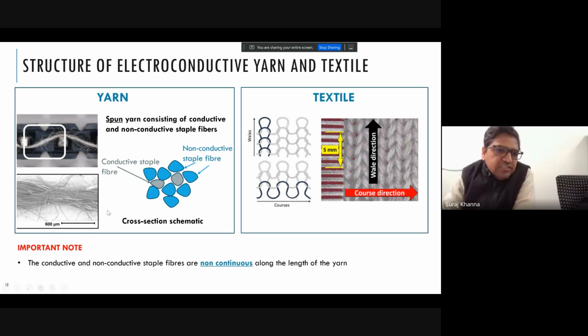If you can see, this is the yarn, and since these yarns can't have rigid contact, we have initially used soft contact. So these are the soft pressure contacts. This is one electrode, this is the second electrode where the contacts are forming, and this is our DUT, device under test, that we have measured.